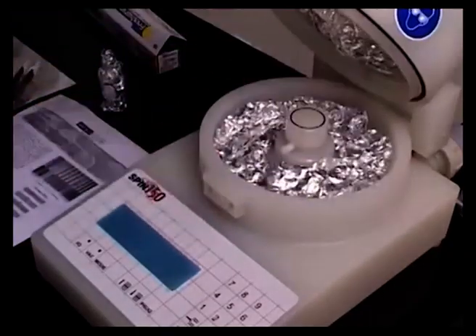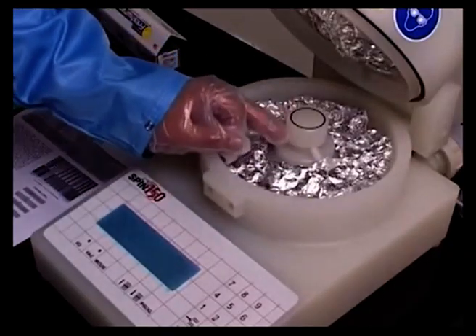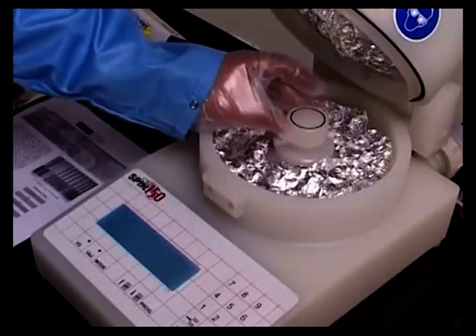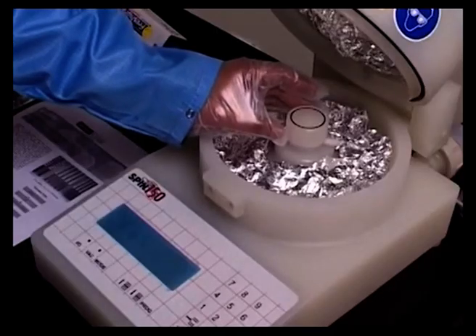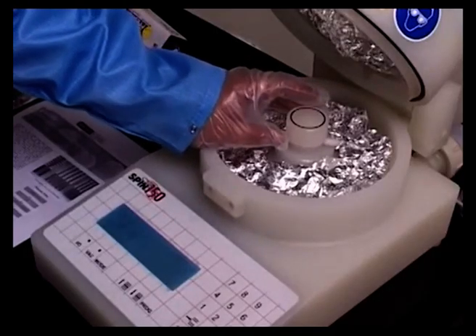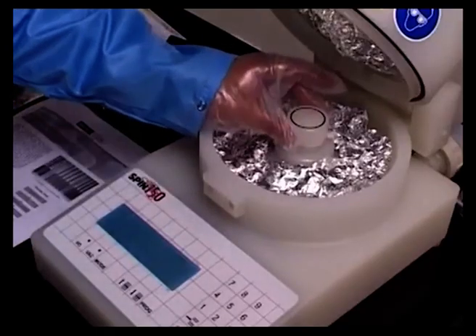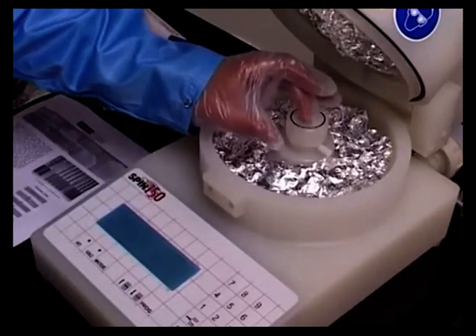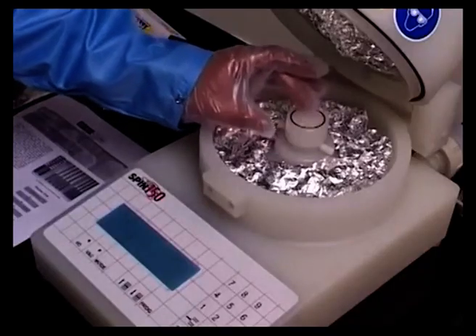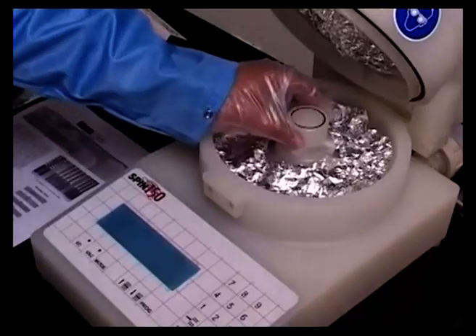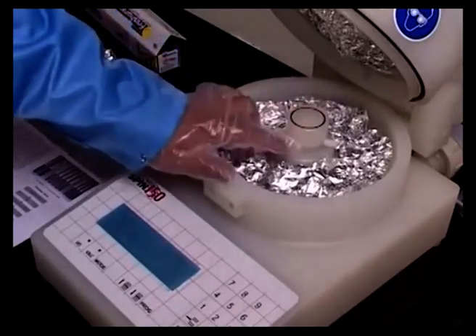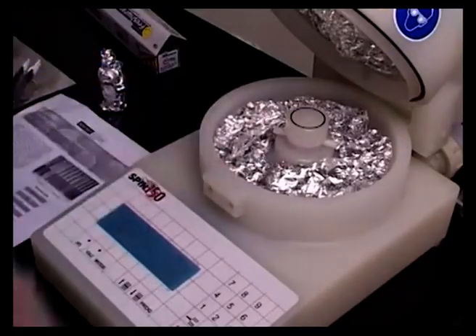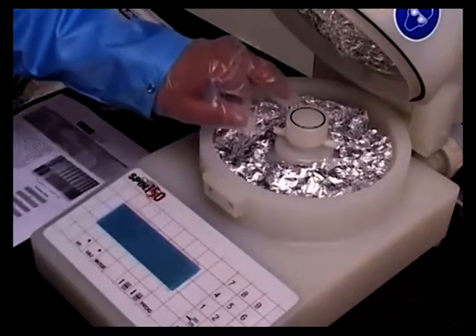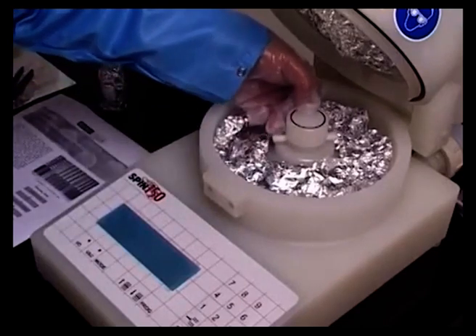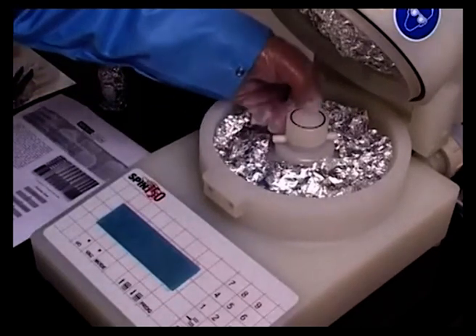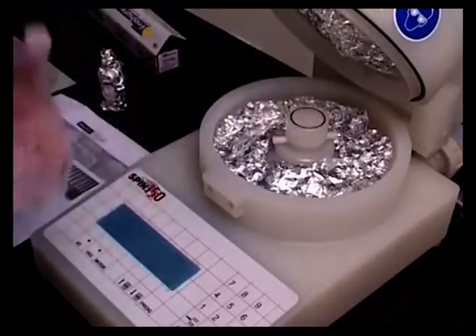Essentially, if you look into this machine closely, you have a spin stage, which is represented here in this area. The principle is that you use vacuum for holding the wafer onto the spin table. If you look closely into this area, you have these grooves which are crisscross, and they are placed over the whole periphery of the spin stage. The purpose of these grooves is that there is a vacuum track immediately below this, which is connected to a vacuum pump underneath the whole system, and the vacuum propagates all the way up through this small center hole, and also along these grooves, and holds the wafer on top of this surface.